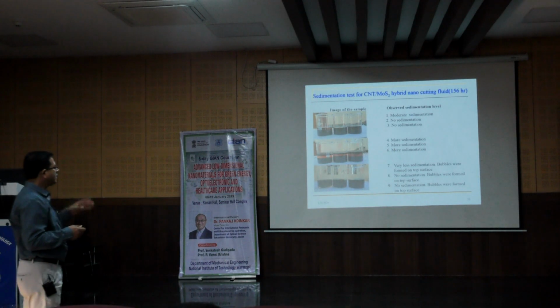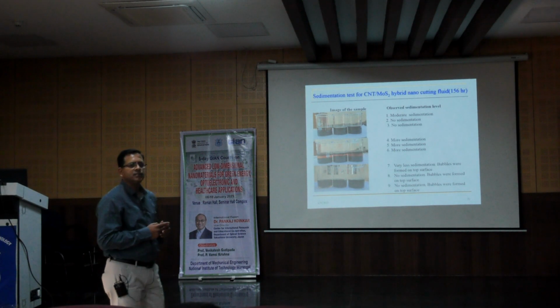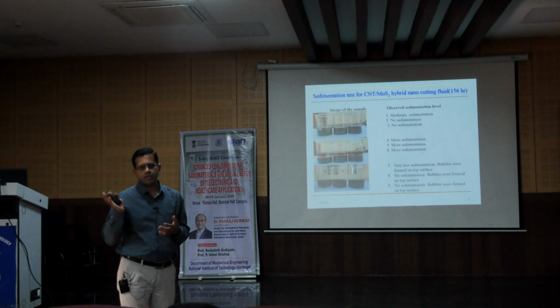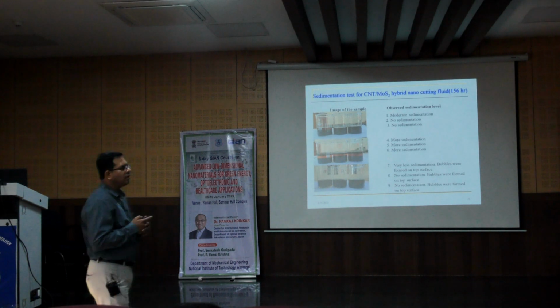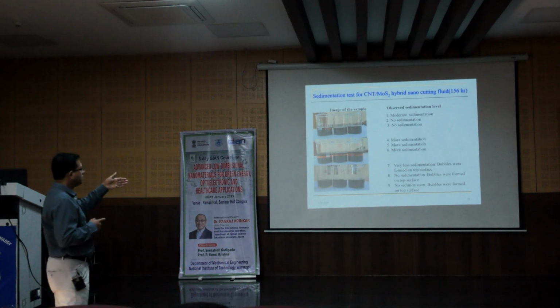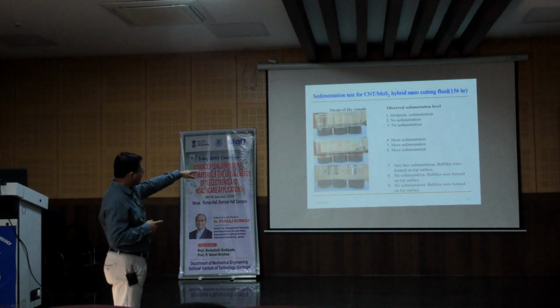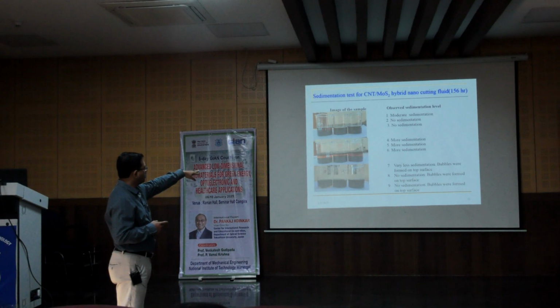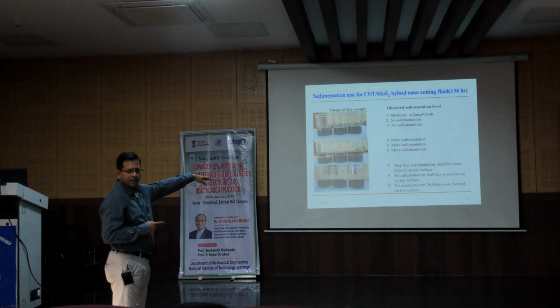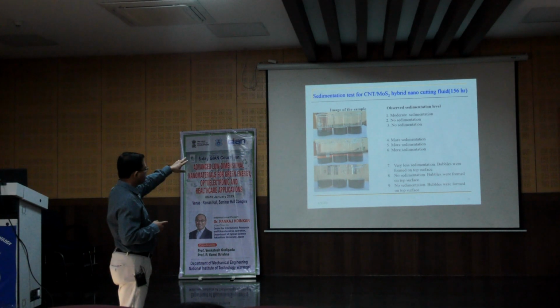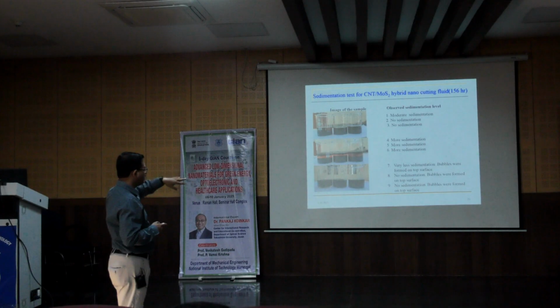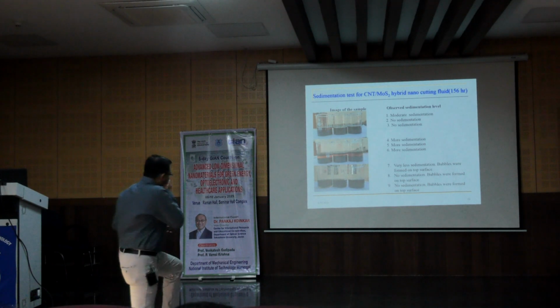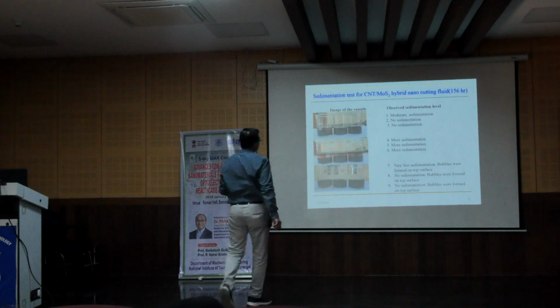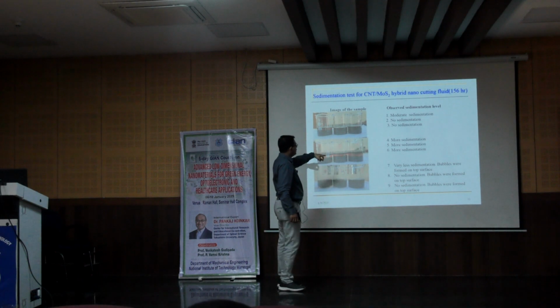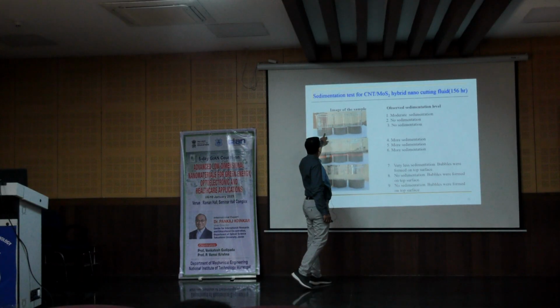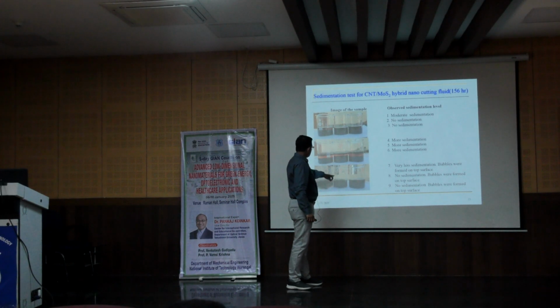Then these are the tests. This is a sedimentation test, after 156 hours. Before going for the zeta potential test, we just observe this, right? This is what we observe. Some particles are coming down and settling at the bottom, so sedimentation is taking place. If you observe here, more sedimentation is there, and here no sedimentation, here also moderate sedimentation is there, and here also no sedimentation.